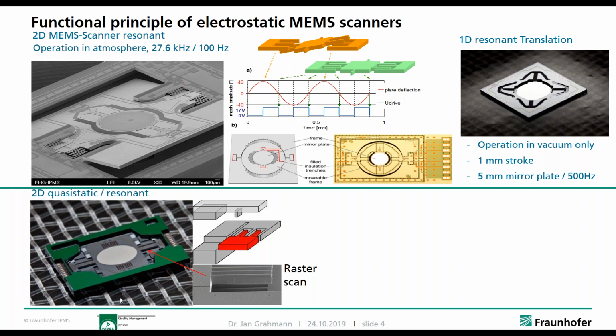Then down here, we basically have an extension of that technology towards a quasi-static one. Quasi-static in this case means we can drive the mirror not just at a certain scan frequency that has to be basically sinusoidal, but we can also drive it in a triangular mode. We can drive it to a certain position and hold it there. So that means we have a quasi-static actuation of that mirror. And in order to achieve this, we do need an offset between the 2 comb electrodes. So up here, you see that they are in plane. In order to get a quasi-static actuation, one of the electrodes has to be out of plane.